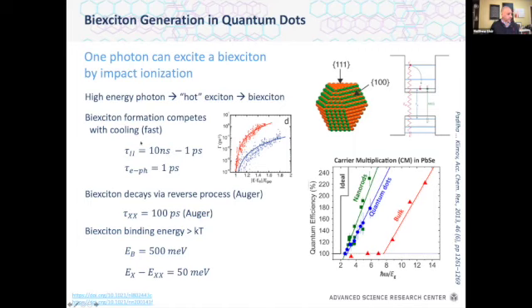There are efficient one electron cooling processes that compete with biexciton formation. The other really important thing to note is that biexcitons are not particularly long-lived because there's a really efficient Auger recombination channel where one of these excitons will annihilate by returning to the ground state. The other one will gain the excess energy and just be hot again. And so, again, all of these numbers depend, as things do at the nanoscale, on the shape and on the engineering, on the overlap of the electron and hole.